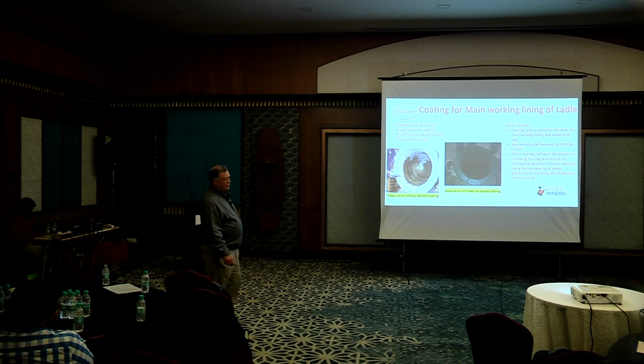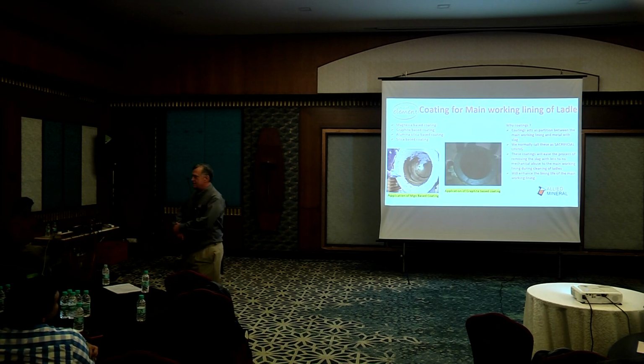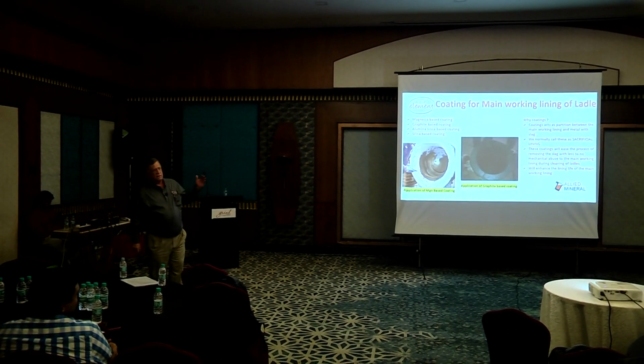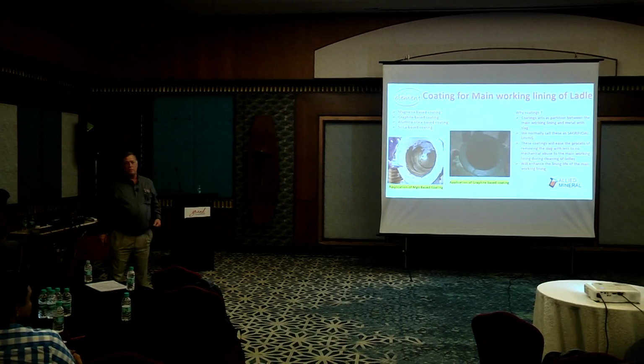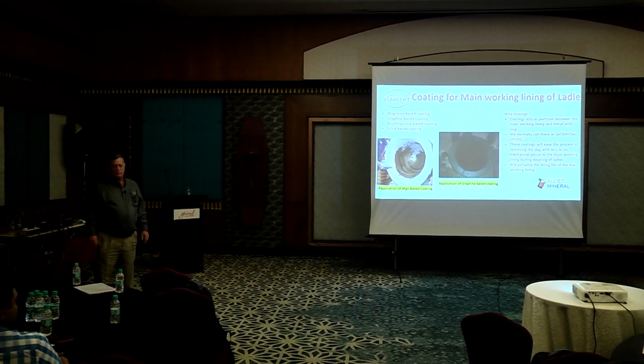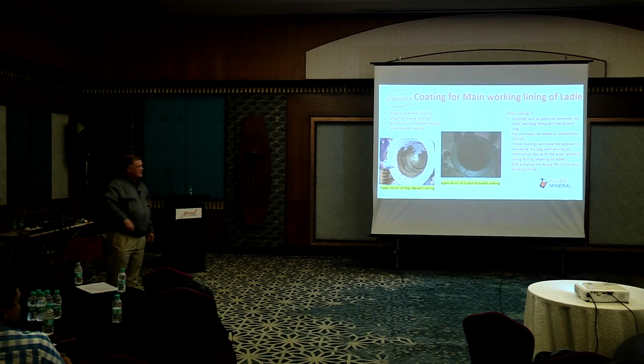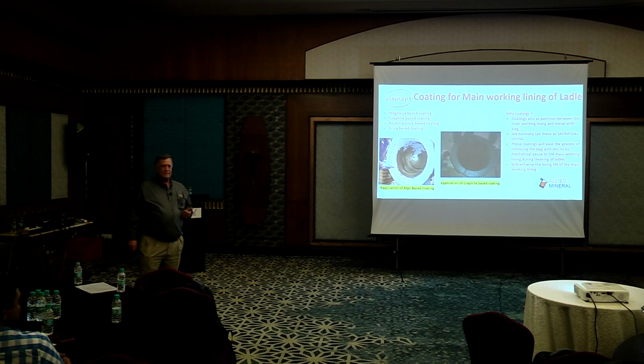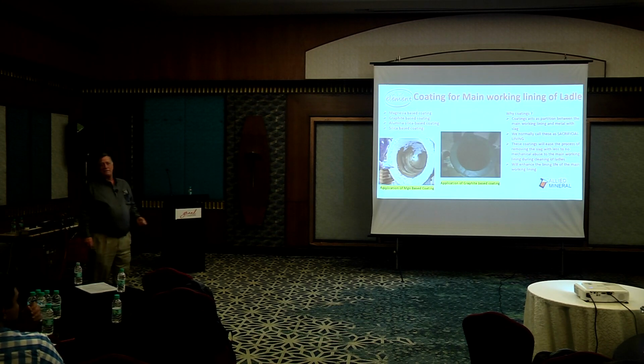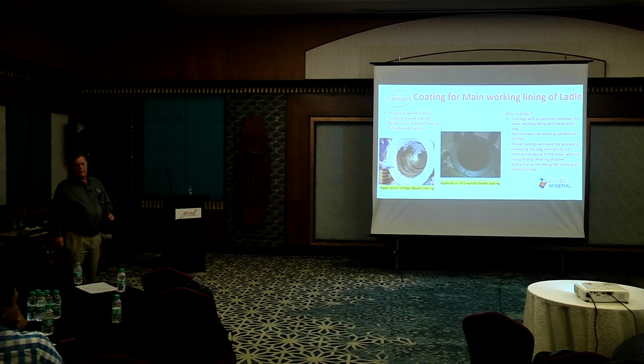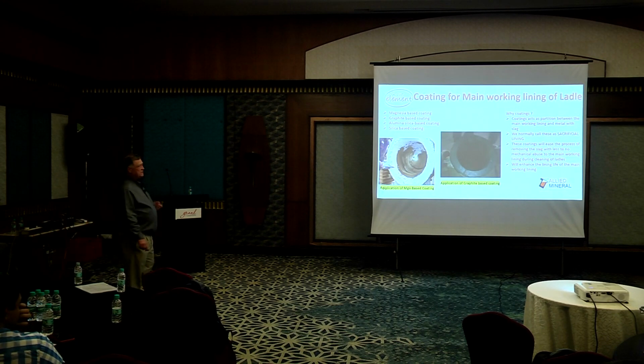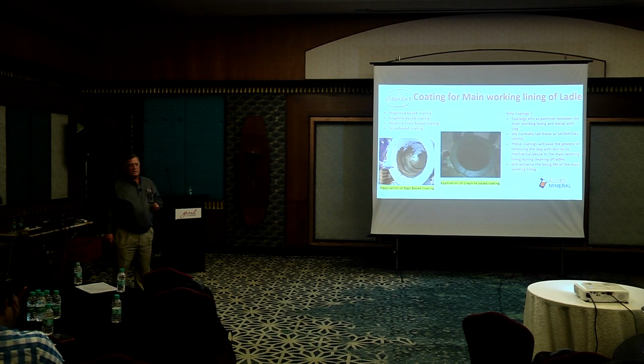There's also coatings that can help you. Like I was talking about earlier, sometimes the standard process in India is, okay, we're going to use this product, and we're going to use that exact same product as a coating every time we cool the lining down. Well, castables aren't designed to be cast and troweled. They're designed to be cast. At casting water rates, you get your maximum density, less porosity, higher strength. So in order to trowel it, you typically have to add slightly more water, or you sift out the large grains and then put it on so it's finer. So what you've done there is you've taken away the large grains.